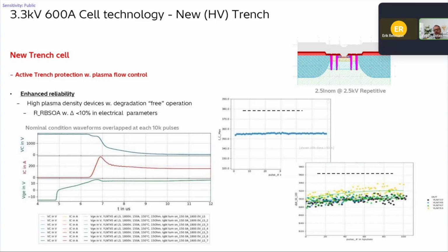So an internal figure of merit is that we run at least 100,000 such SOA pulses, and we look at the turn-on di/dt, and this is our limit. So we want to see that this is as stable as possible under these conditions.